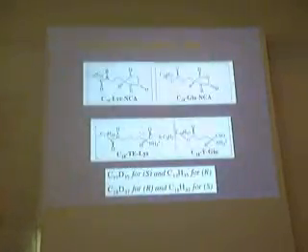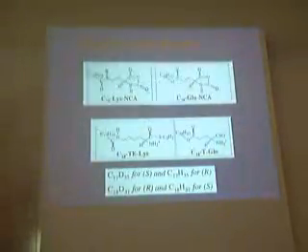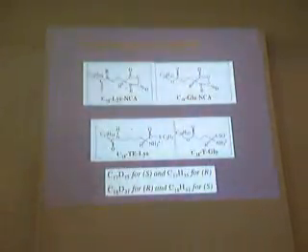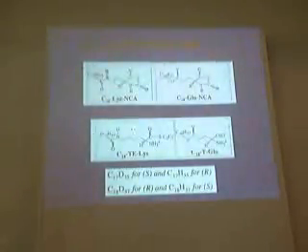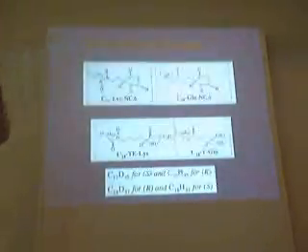Now, the method that we are using, and I shall come back also to Luigi's studies, which is also using this part. We have used that method also for mapping disordered racemic crystals by labeling one of the enantiomers with deuterium. If you label one of the enantiomers with deuterium, they have different molecular weights, and if you go to MALDI-TOF, it is possible to actually determine the distribution of the various diastereomeric peptides which are formed.